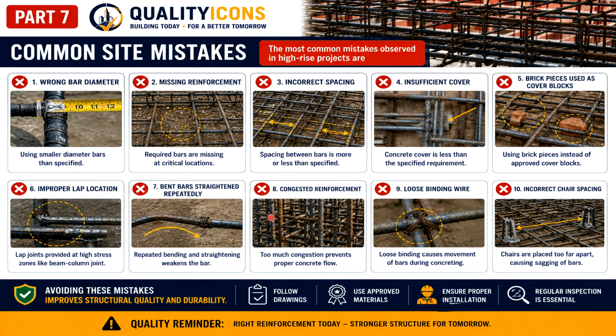The second mistake is incorrect bar spacing. Closely spaced reinforcement causes congestion and poor concrete compaction, while excessive spacing reduces structural performance. Another common issue is insufficient concrete cover. Without adequate cover, reinforcement becomes vulnerable to corrosion, carbonation, and fire damage. Improper lap locations, missing reinforcement bars, loose binding, damaged cover blocks, bent starter bars, and unauthorized cutting of reinforcement.